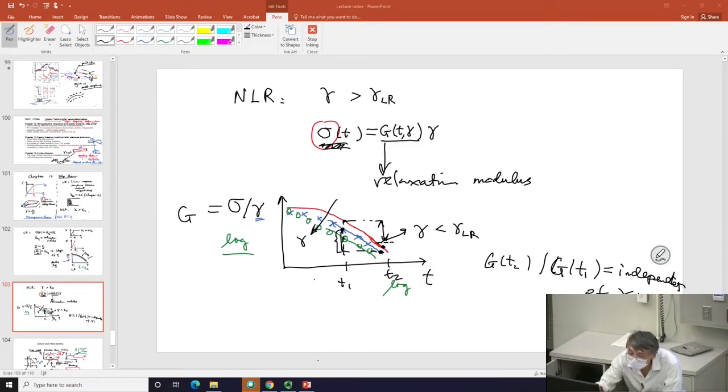So experimentally, we discovered long ago, since 70s, that at least after some point called TK, for some historical convenience or historical reason, after this point, these three curves are the same apart from a vertical shift.